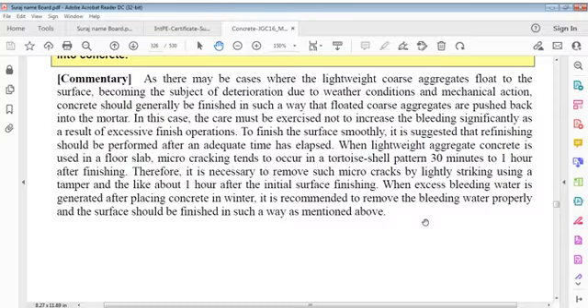As there may be cases where lightweight coarse aggregates float to surface, becoming subject to deterioration due to weather conditions and mechanical action, concrete should generally be finished in such a way that floated coarse aggregates are pushed back into mortar. In this case, care must be exercised not to increase bleeding significantly as a result of excessive finishing operation. To finish surfaces smoothly, it is suggested that refinishing should be performed after an adequate time has elapsed.